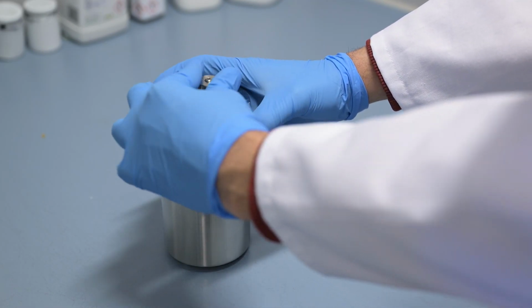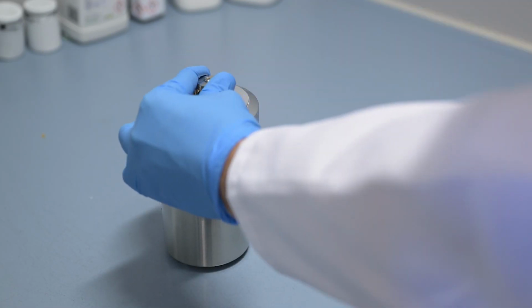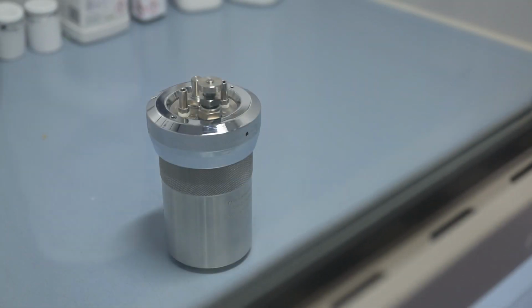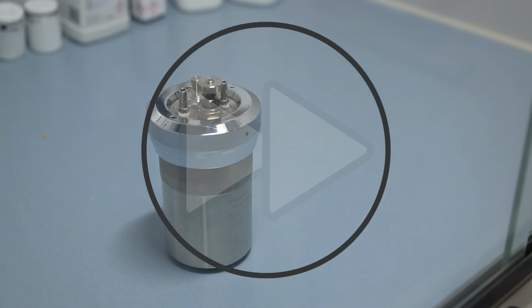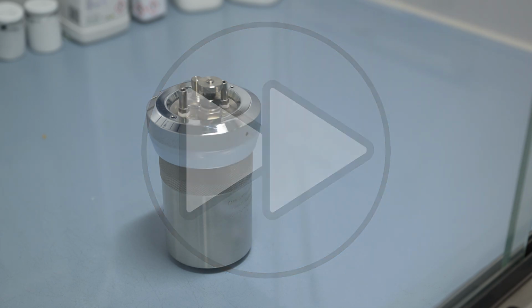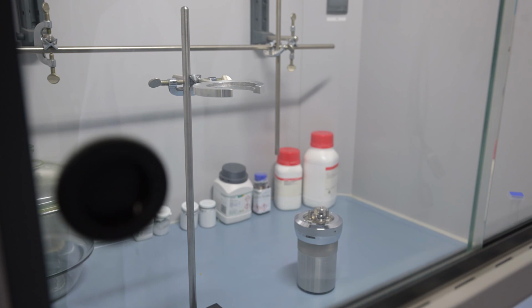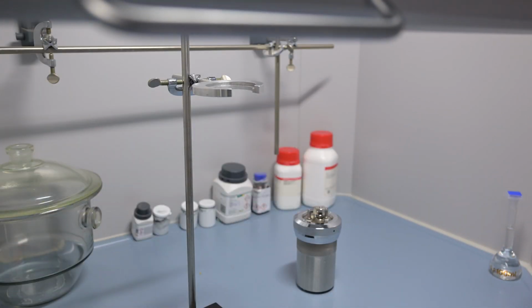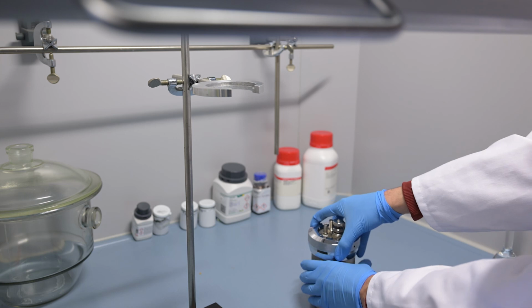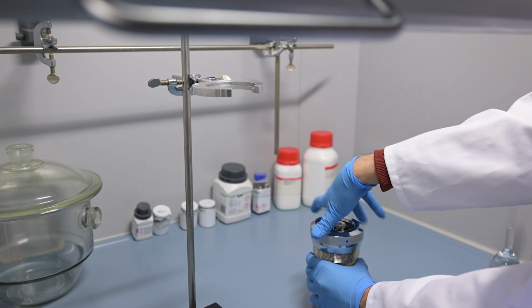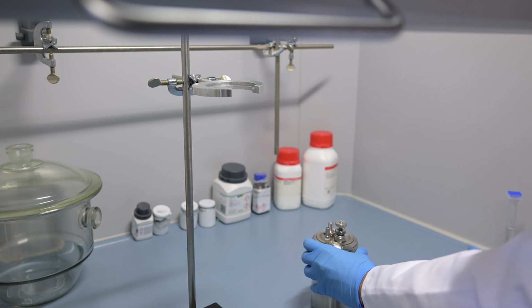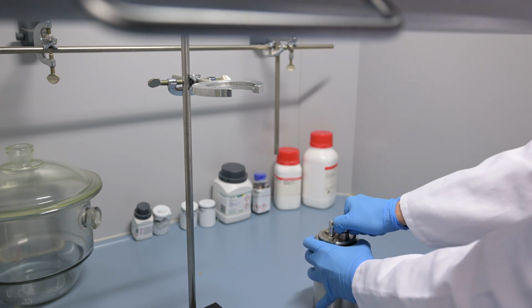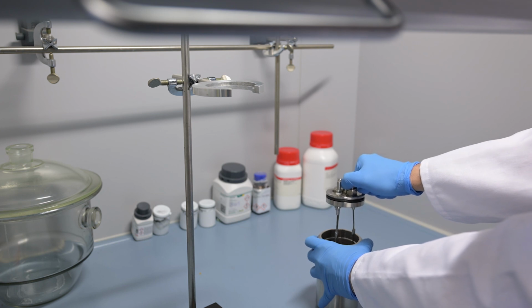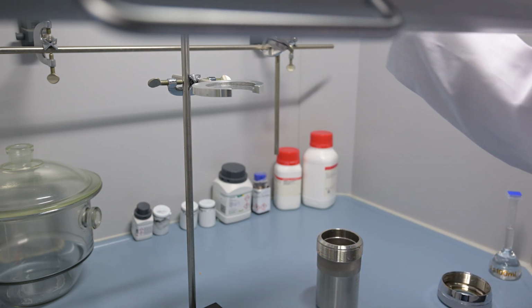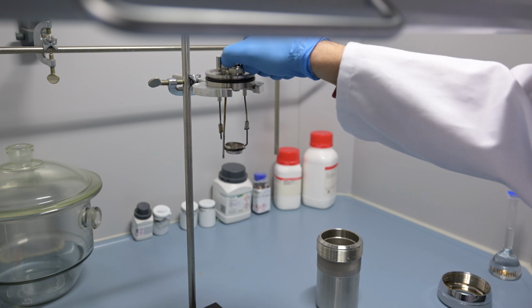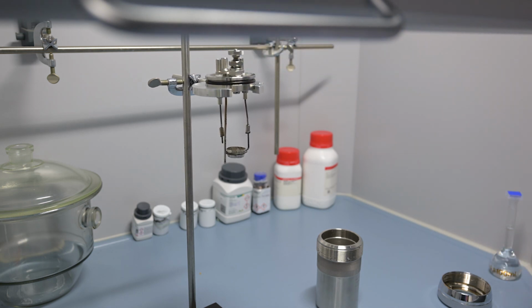After the experiment, it's important to collect the liquid inside the pump vessel, starting by releasing the oxygen under a fume hood for around 1 minute. After that, open the pump and assure that there was a complete combustion. If no black dots are spotted, that means complete combustion has been fulfilled.